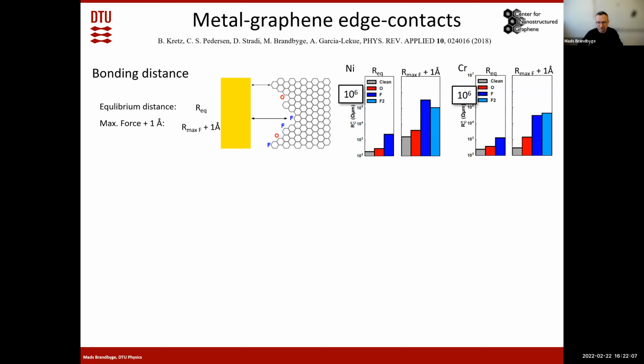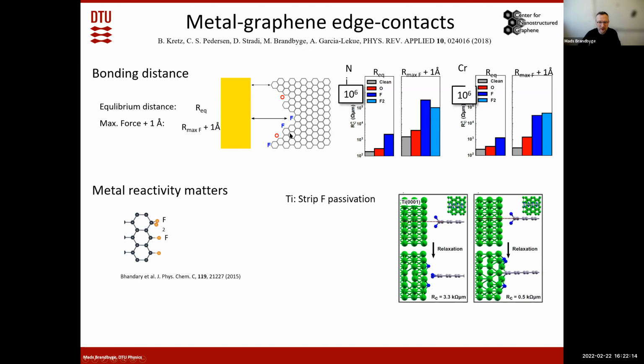So we guess that both the passivation, but also the fact that you do not have a straight edge here plays a role. And then from the calculation, we see one more thing, and that is that the metal reactivity probably also matters when you make the contact between the metal and the graphene. Because if the graphene is passivated by, let's say, fluorine, then once you take a metal and make contact to the graphene with the fluorine on, if the metal is reactive like titanium here, then it's able to strip off the fluorine sitting there and make a cleaner contact, getting a lower resistance. So there are some factors we need to be able to control in order to really optimize these contacts.